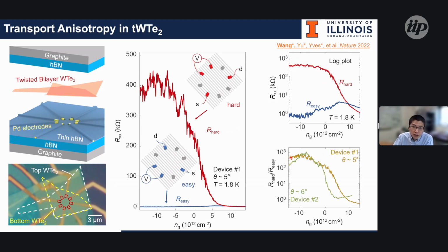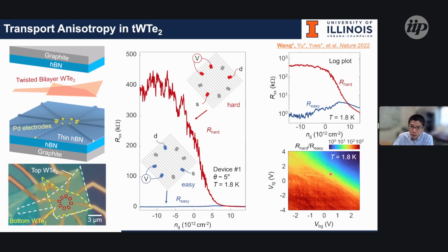We can confirm this phenomenon by simply dividing the hard resistance by the easy resistance along both directions. You can get the ratio of this anisotropy going up to around 1,000, and even higher if you cool the sample down to much lower temperature.